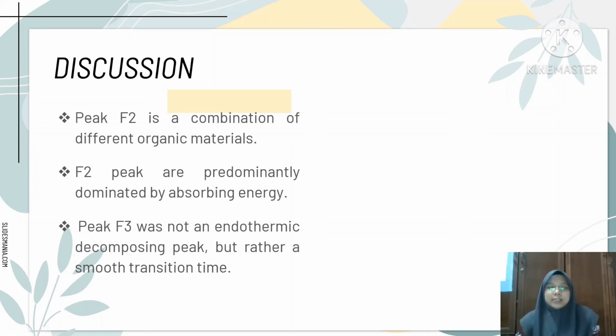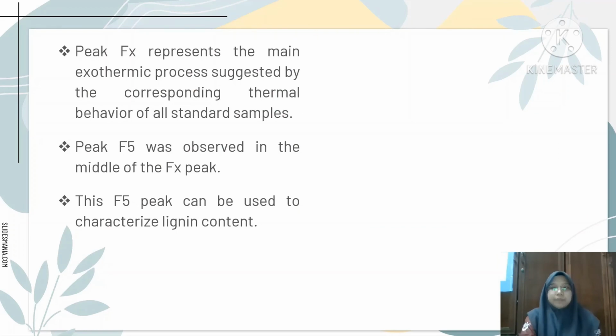With each component and total organic matter, the absorbed heat of peak F3 was poorly associated, indicating that peak F3 was not an endothermic decomposing peak but rather a smooth transition time. Peak Fx represents the main exothermic process suggested by the corresponding thermal behavior of all standard samples. Peak F5 was observed in the middle of the Fx peak. Instead of an endothermic pyrolysis peak, peak F5 reflects the difference between exothermic processes. Nevertheless, this F5 peak can be used to characterize lignin content.